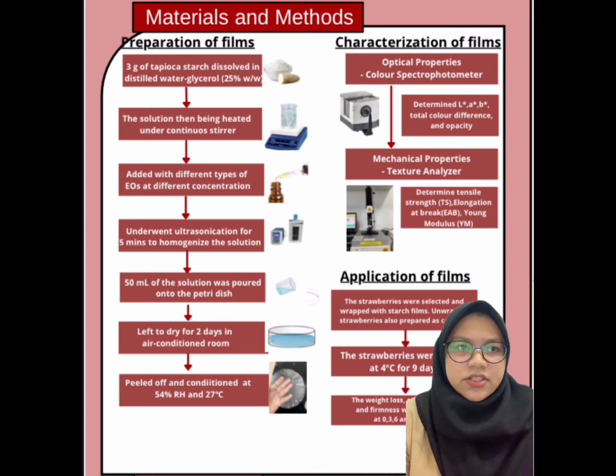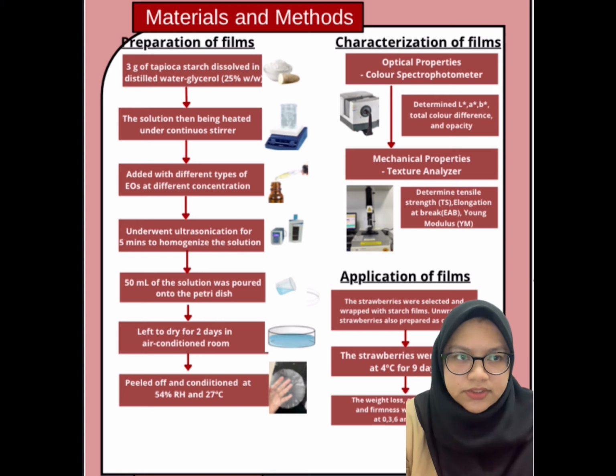As for the application of the films, the strawberries were first selected and wrapped with the films. Unwrapped strawberries were also prepared as a control. Then the strawberries were stored in a chiller at 4 degrees Celsius, and the weight loss, color changes and firmness were evaluated at 0, 3, 6 and 9 days.